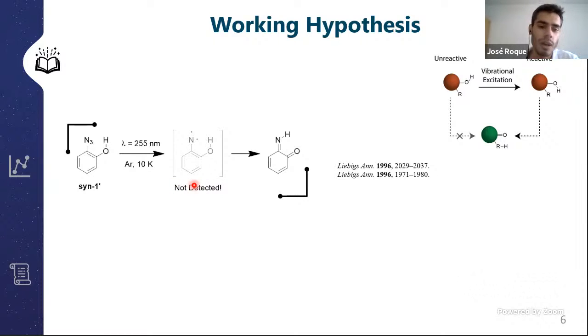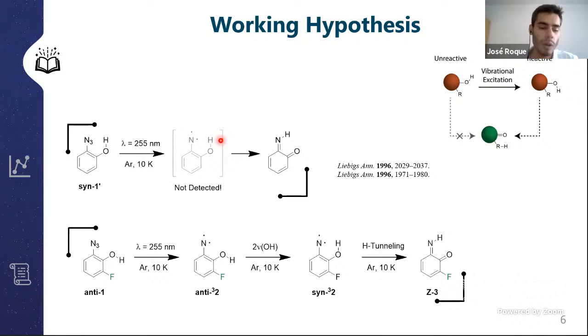And the reason we believe now that they couldn't find this nitrene is because the OH group is very close to the nitrene center, and therefore allows a fast migration of the hydrogen atom. So our proposal was to introduce a fluorine atom adjacent to the OH group, which should stabilize the anti conformations through an intramolecular hydrogen bond. And from there, we would proceed to produce the anti-nitrene conformations by irradiation with UV photons,